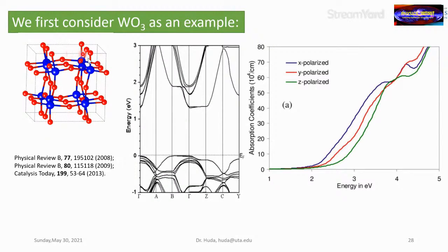For this tungsten oxide structure, we calculated its band structure. So this is the band structure, as you can see. Now, anything below zero is occupied. We call them valence band. Anything above this line is the conduction band, unoccupied. Hence, if light comes, let's say solar light comes, electrons will be excited from the valence band to the conduction band. This plot on the right side is the optical absorption coefficient, or you can think of it as an absorption probability, or electron excitation probability, from the valence band to the conduction band.